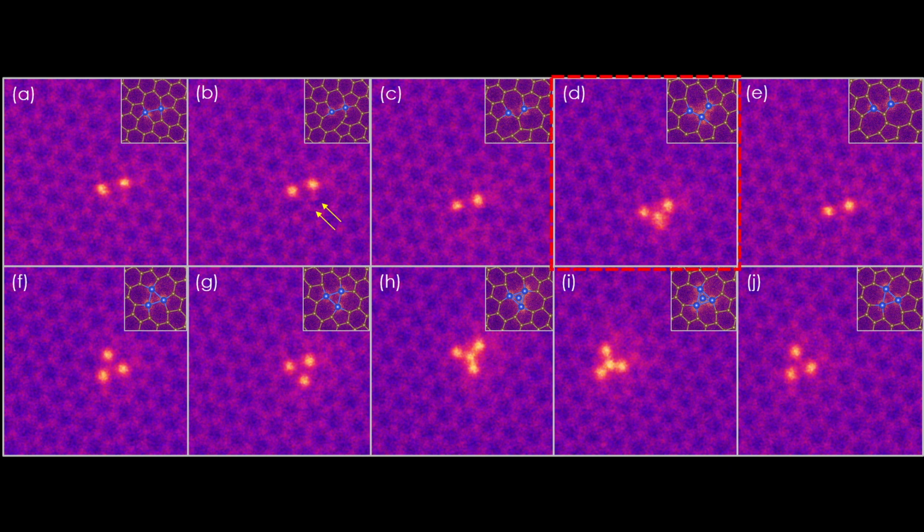After the rotation, a third silicon atom diffused into the field of view and attached temporarily to the rotated atoms. The influence of the electron beam quickly knocked it away again. It returned a few moments later and then replaced one of the carbon atoms involved in the bond rotation, likely due to the added energy of the beam. The result is a silicon trimer that can easily be rotated by positioning the beam next to it, shown in these two panels.